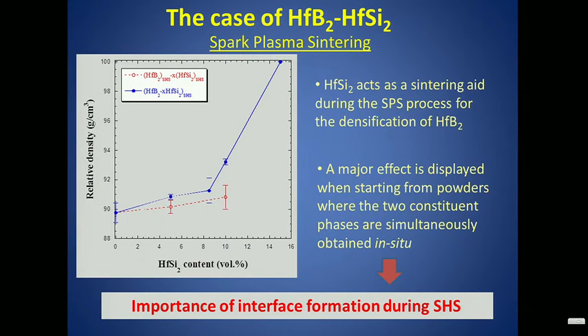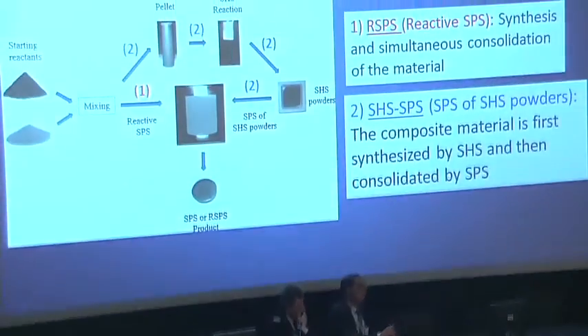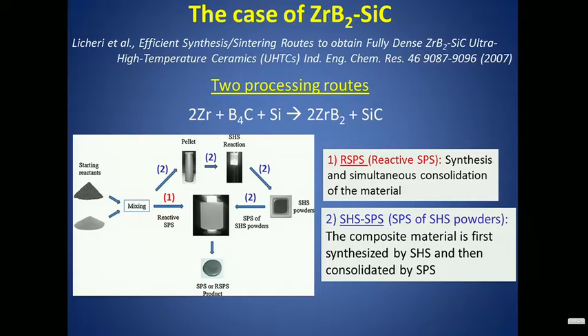On the other hand, if you go and sinter these powders, you see the difference. You have a much better sinterability if you produce the two constituent phases simultaneously, in situ. So the formation of the interface is very important. Let's take a look at another system, zirconium diboride, silicon carbide. In this case, you have two possible processing routes. One is the so-called direct RSPS, reactive SPS, where you consolidate and react the starting powders in one step. Or you go through route 2, where you get the products through SHS and then you sinter them.